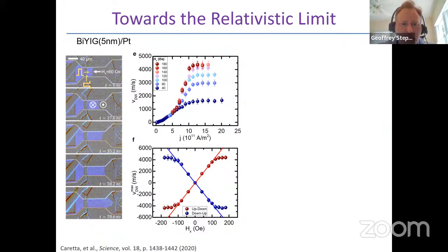spin orbit torques. And so the collection of figures here that you see on the left is the velocity versus current, where you see this plateau. And that plateau, at least for low in-plane fields, is proportional to the stiffness of the wall. And the bottom figure shows that plateau velocity as a function of in-plane field. So the stiffer the wall is, the faster it can move, but there's always some limit.